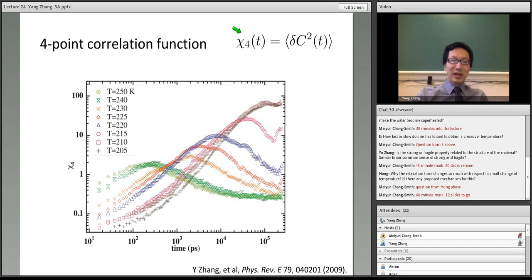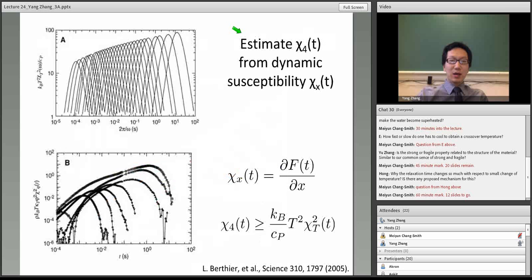Another way to access chi4 from experiments is by looking at the so-called dynamic susceptibility. Again, chi4 cannot be directly determined from the scattering experiment, but what we can determine is the intermediate scattering function, which is basically a 2-point correlation function. Recently, people have proposed that if we know this 2-point correlation function f, and vary certain control variable of the system, like x here, either temperature or pressure or volume fraction, we can use this so-called dynamic susceptibility to estimate the lower bound of the 4-point correlation function.